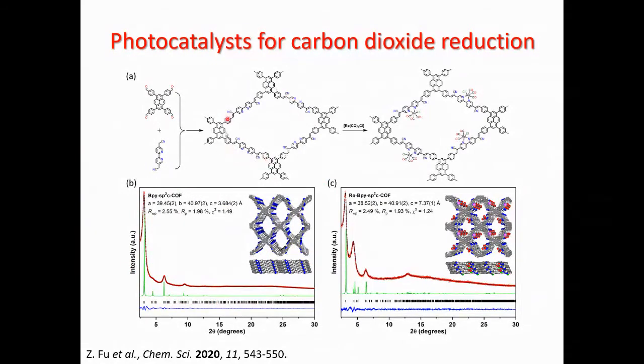As I said, with these systems, we were really keen on avoiding having palladium present in the system. That's why we used this condensation reaction, but we would need something else to actually facilitate the CO2 reduction in the end. So we loaded onto these systems some rhenium complexes that are able to ligate to these bipyridine ligands instead. Also, it allows us to selectively load the systems rather than the palladium chemistry. After the loading, we can see we still have really defined XRD patterns here. And again, the models indicate that we have layered AA stacking type materials.